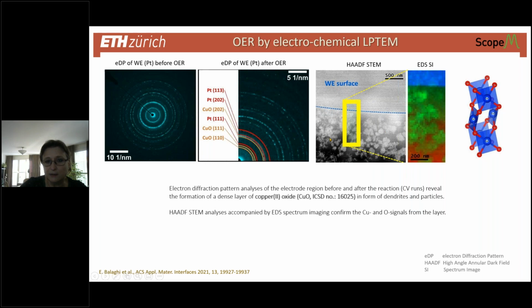Now, we analyzed these particles. This is now an HAADF STEM micrograph, so a high angle annular dark field image. And you see now the dendritic morphology of the large number of particles in the image. And this is post-mortem, so post-reaction analysis. But first, we just have to look at the electron diffraction data. Now, we have the electron diffraction pattern of the working electrode. In this case, it's platinum before we ran the scan. Then the electron diffraction pattern of the same electrode after the reaction shows immediately that we have different phase formations.